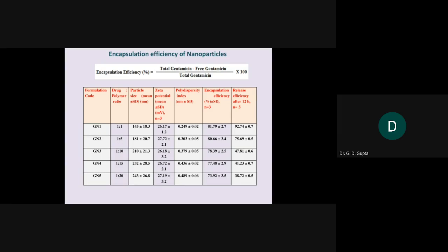Now we prepared 5 formulations, as you can see in this table. This is GN1, GN2, GN3, GN4, and GN5. The drug polymer ratio is presented here. You can find the particle size also. The minimum average particle size was near about 145 nanometer, and the biggest one was GN5, with an average particle size of 243 nanometers. And the zeta potential, you can find, is between 20 to 30, and the polydispersity index, as you see, is 0.2, 0.3, 0.3. The polydispersity index value is not very good, but it's okay, we can say the particles which are formulated were nearly uniform in size.